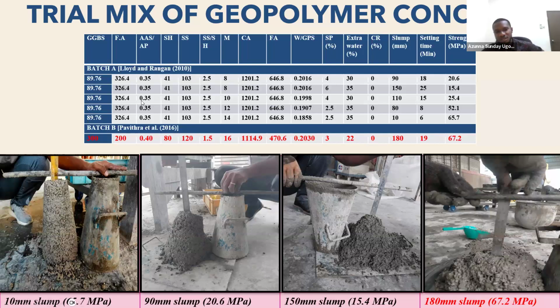So the first method, I used the density method by Lloyd et al. If you look at it, my alkaline activator solution to precursor ratio, I used 0.35 all through. And my binder content wasn't so high though, but it's supposed to give also a very good strength. Then I'm going to be emphasizing on the slump, the setting time, and the strength. So if you look at all the test results that I got using the density method, there is no balance. Now, if you look at the first one, the first mix has the slump of 10 mm.